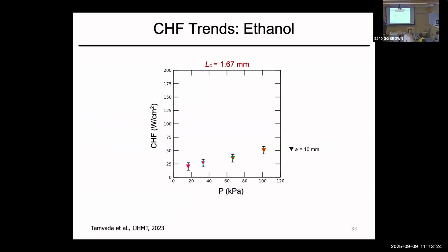If you start with ethanol, with the capillary length of 1.67, and you do a 10 by 10 heater that everybody tests, as a function of the pressure, you can predict it on a flat surface using Zuber theory. Now you go to a 2 millimeter, which is right above the capillary length. You go to 1, and then you go to 0.5, you see no change. Once we reduce the width below the capillary length of the fluid, you see no change in the CHF.